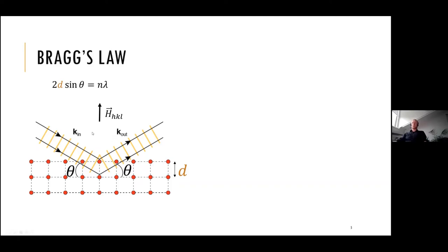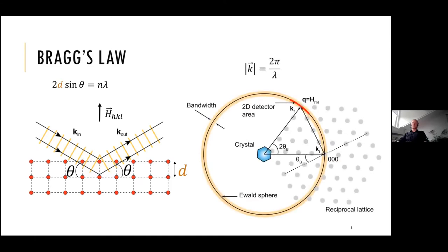This is the simple drawing showing how the experiment actually goes. In another way, we can describe the diffraction from the crystal by constructing the so-called Ewald sphere, which is based on two vectors: Ki, the incident wave vector, whose modulus is 2 pi divided by the wavelength, and Kf, a scattering vector separated by 2 theta Bragg, the Bragg angle for a given crystal.